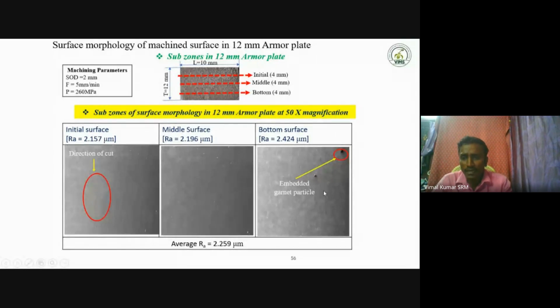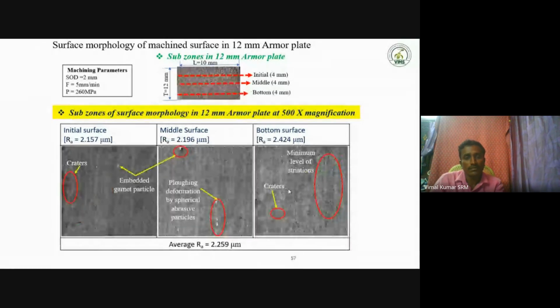Here embedded garnet particles are placed on the top surface. They are identified in the SEM image, but they are not fixed in the cut surface of the material. So here 2.157, 2.196, 2.4 are acceptable, because in the SEM condition the finish is visually a very good surface as compared to the flame cutting process. So, the 12 mm plate.